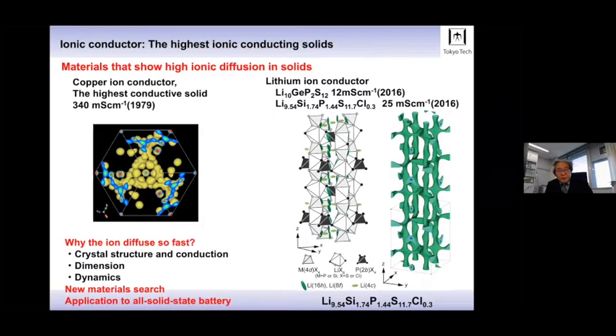The most important part of the solid-state battery is the electrolyte. A material that allows ions to diffuse in a solid at high speed is called an ion conductor. Currently, the material with the highest ion conductivity is the copper one. Its ion conductivity at room temperature is about 0.3 Siemens per centimeter, which is about the same as that of an aqueous solution electrolyte. The highest conductivity among lithium-ion conductors is the LGPS-type materials shown here. It has a value of 10 to the minus 2, which is one order of magnitude lower than the copper ion conductor. The continuous distribution of lithium ions in the structure can be seen. This is the so-called super ion conducting state.